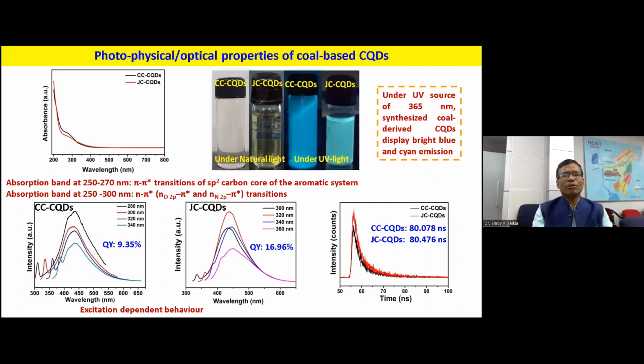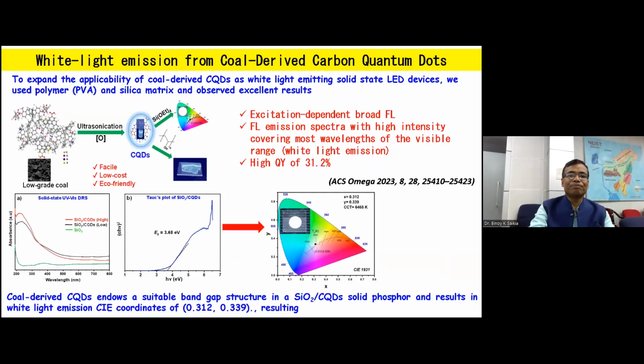But we also tried to change this emission, and we found a little bit of change in the color. You can see in a different coal it goes a little bit to a greenish cyan emission. So that can also be done, but I find it challenging because of the sulfur and nitrogen doping, to make a different emission. So another work is going on, how to make it red or other emissions. This is interesting, and this work is going on.